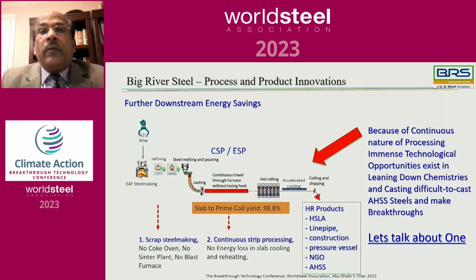And because of this continuous nature of processing, immense technological opportunities exist because it's a thin slab caster, and also low soaking temperature and very little residence time inside the furnace. That gives us, as product metallurgists, the ability to lean down the chemistry, and also the benefit is that CSPs can cast difficult-to-cast advanced high strength steels, which otherwise in the integrated way of making, one has to cool down very slowly and also practice reheating back to the soaking temperature. That is avoided in continuous CSP minimill steel making.